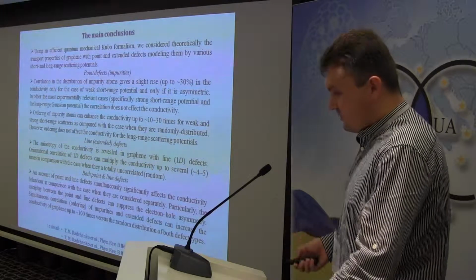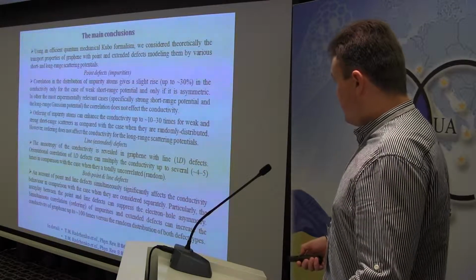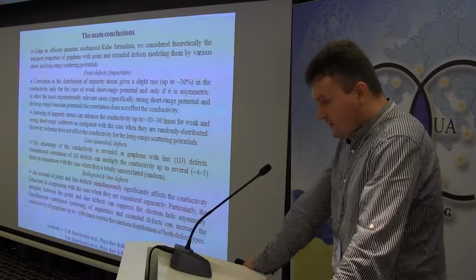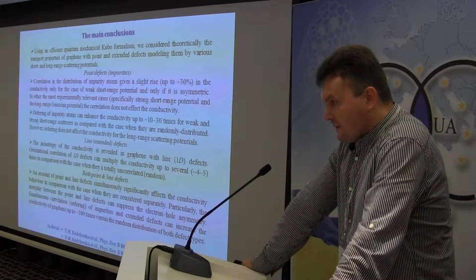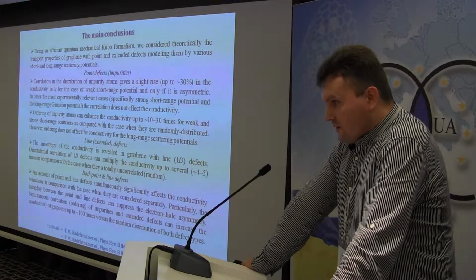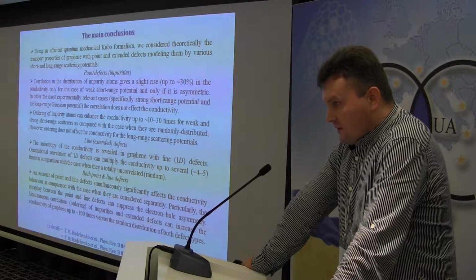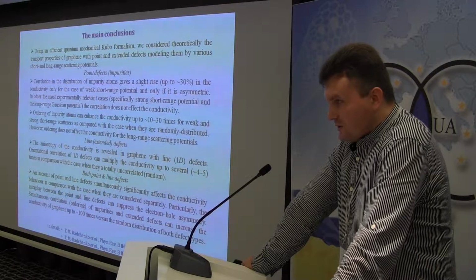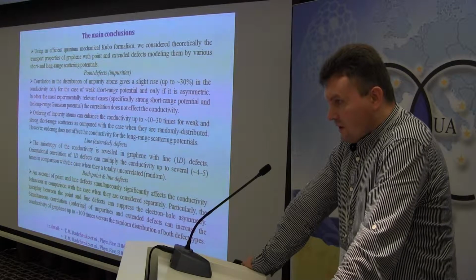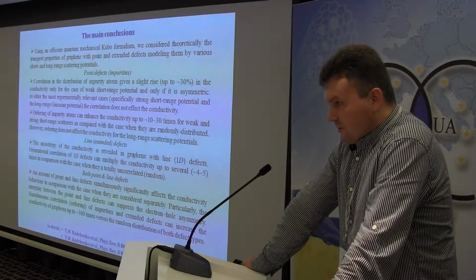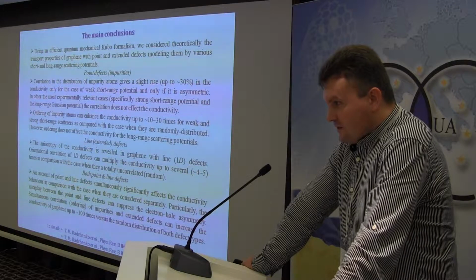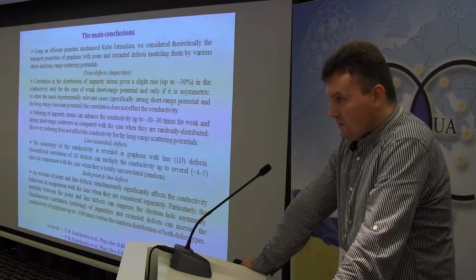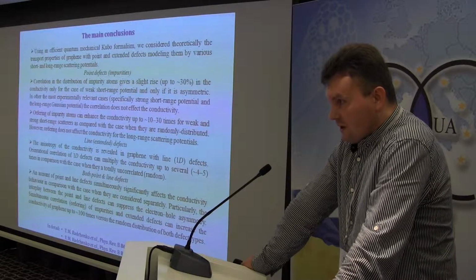I will not read this conclusion. I only say, to summarize, that if defects are described by a long-range potential, correlation or ordering effects are absent. But if defects are short-range, we can see that correlation and especially ordering can increase the conductivity up to several times.